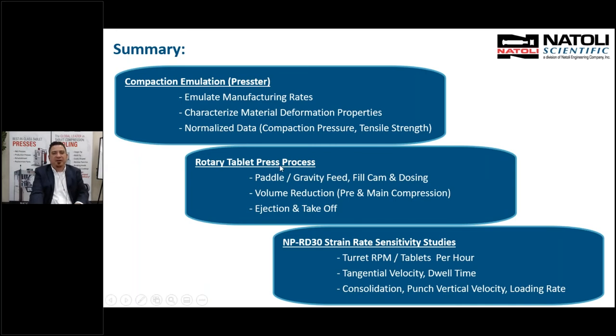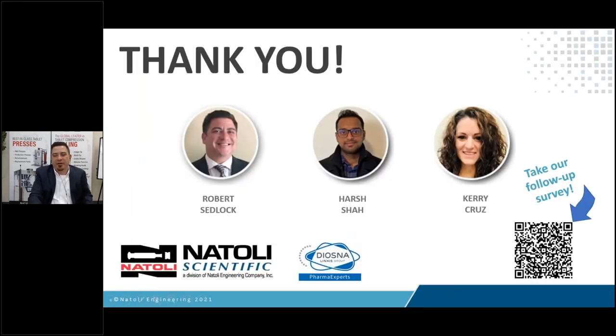And then we talked about the rotary press, the NP-RD30. We looked at the dosing cam, fill cam, that mismatch there, which is very important. We talked about pre-compression, main compression. We talked about ejection and takeoff being two separate stages. If you have an ejection problem, we fix it a certain way. If you're having a sticking problem from a takeoff or picking, we address that a different way, okay? We also talked about strain rate sensitivity studies, where we want to know if our material is sensitive to the loading rate or the dwell time or the tangential velocity, and we normalize all that data as well. Okay. All right. With that, I want to thank you guys for your attention, and I'm going to hand it back over to Carrie.